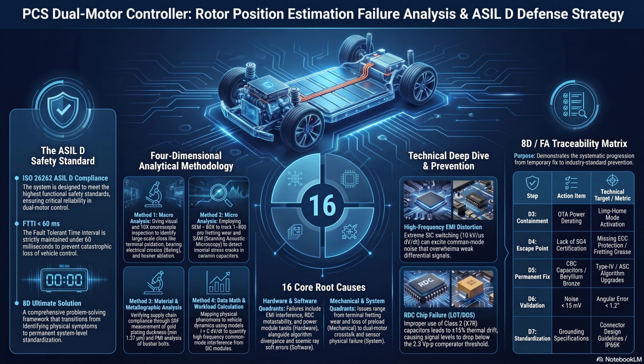Okay, so that brings us to the third dimension, which is material analysis. This is where the investigation shifts toward, like, supply chain validation. Catching suppliers who cut corners. Exactly. The lab deploys X-ray fluorescence, or XRF, to verify the exact thickness of the terminal plating. Right, because the engineering specification for the soft gold plating on these specific resolver terminals is strictly set at a minimum of 1.27 microns.